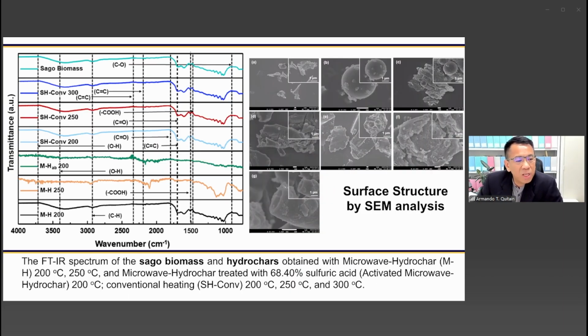These are some of the FTIR spectra that we can get from analyzing the surface of sago biomass hydrochars obtained using our approach, the microwave hydrothermal carbonization. And using SEM and TEM analysis, we also found some amazing structures, like the presence of carbon nanotubes and some spherical carbons present on the surface of the hydrochar we got from sago. Now, the presence of these functional groups on the surface of graphene oxide or even sago hydrochars